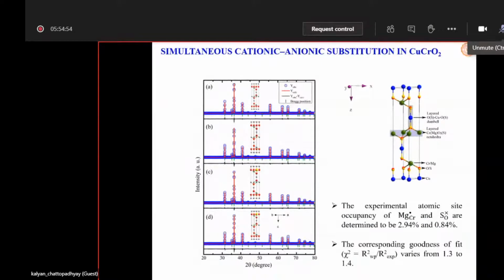Now, for this study, we have taken another system, which is copper chromium oxide. This is again a very interesting, normally p-type material. We prepared this material and introduced different sets of doping. First of all, of course, the pristine sample was developed without any doping, and then we introduced magnesium at the chromium site. Magnesium is bivalent, chromium is trivalent, so you can expect generation of some holes. And then we introduced anionic site doping, sulfur at oxygen, and in another sample we introduced both cation and anion simultaneous doping. So this is the XRD, X-ray diffraction pattern.